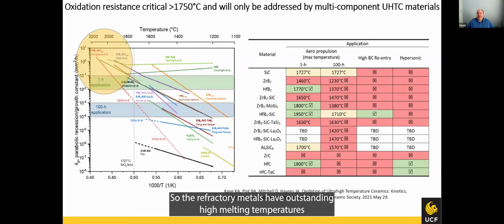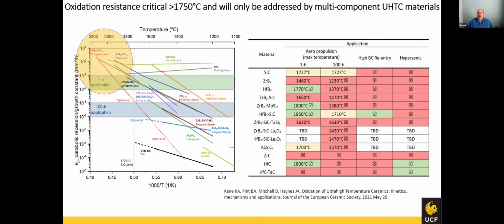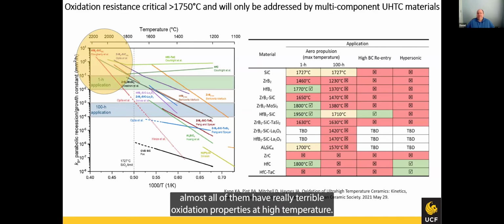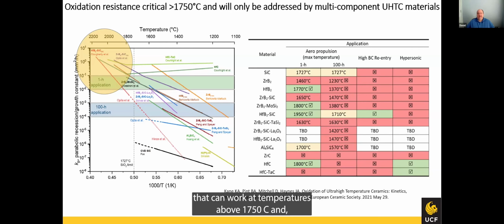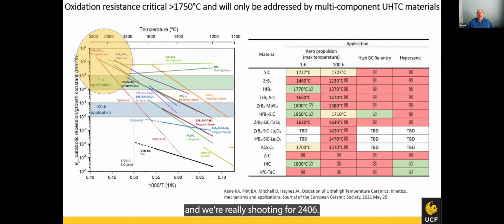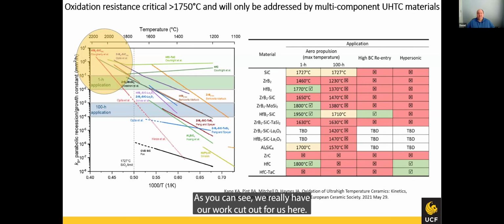So the refractory metals have outstanding high melting temperatures and high temperature strength, but unfortunately, almost all of them have really terrible oxidation properties at high temperature. And so if you look at the straight up zirconium carbides, and things like that, molybdenum is a great material, but again, and niobium, really poor oxidation properties. So I wrote a paper with some friends at Oak Ridge National Lab on oxidation at high temperatures, and we identified some compositions that can work at temperatures above 1750 C, and we're really shooting for 2400 C. So as you can see, we really have our work cut out for us here.